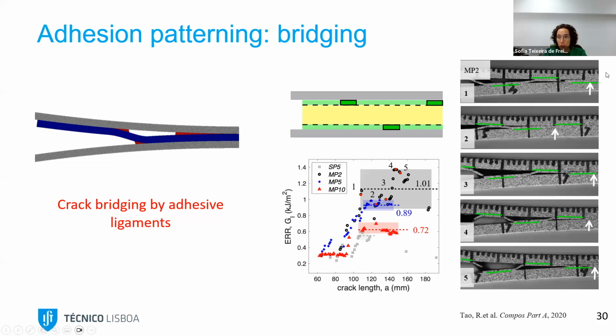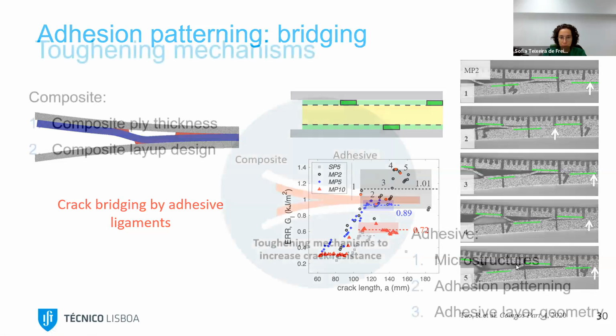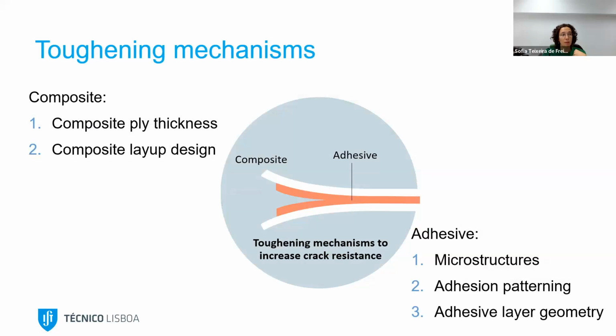By doing that, here you see the different interface regions and the ligaments that have been done to arrest the crack front. So here you see a similar phenomenon. We have more than one fracture surface and more than one crack tip location. And if we plot the energy release rates against the crack length, we see that indeed there is an increase from 0.72 up to 1 kilojoules per square meter using these bridging mechanisms of using the adhesive and the interface patterning. So not always a defect can work against us. We can also use it to architect the material and the interface.